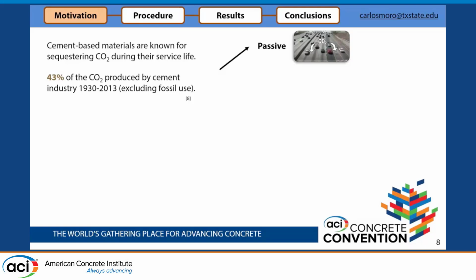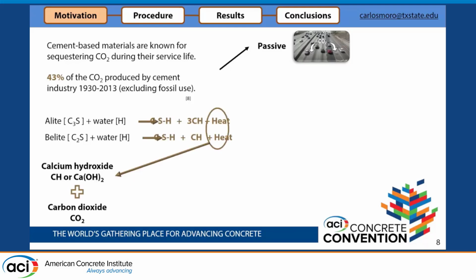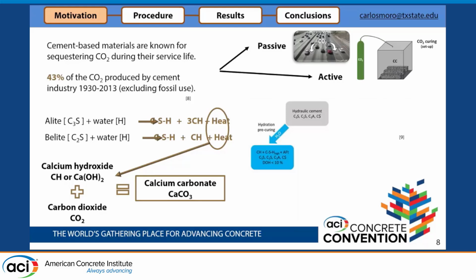And in order to analyze different CO2 capture in concrete, there are two main methods being used. One is the passive, that is the natural carbonation that happens every single year. It's a really slow process. The other way, in order to accelerate this, because we cannot wait 40 years, is the active carbonation. That means that we are promoting this CO2 capture, especially at an early age. The good thing about this is that it not only increases the CO2 capture, but also improves other properties, like compressive strength, durability, and other things in the long term.